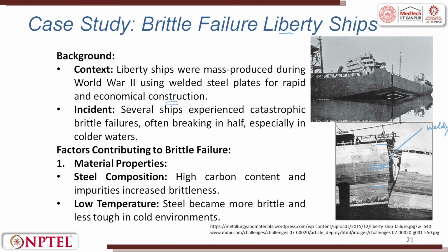Okay. So, the incident: several ships experienced catastrophic brittle fracture, often breaking in half, especially in cold water. The factors contributing to brittle fracture are, first, material property: steel composition, where high carbon content and impurities increased brittleness. Second, low temperature: the steel became more brittle and less tough in a cold environment. Cold environment means in the minus range.